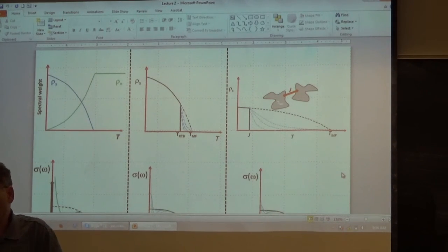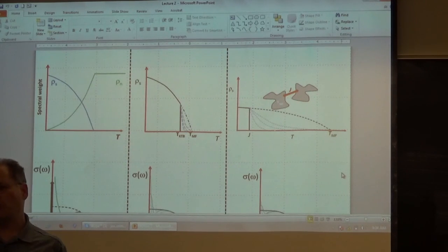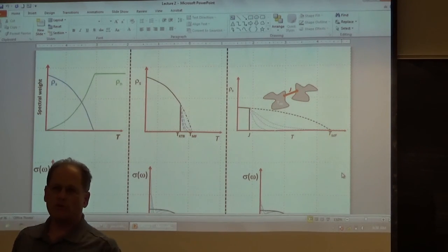I think that one of the interesting things about the cuprates is it enabled some very good experiments to be done by being able to work in a frequency regime where you could scan the frequency. Like conventional superconductors, these characteristic frequencies scale down to the microwaves. And for microwave spectroscopy, essentially, unless you do some very special things, you need a specific cavity setup for a specific frequency. So I've got a laboratory for 10 gigahertz, and if I'm really rich, I can have a laboratory for 10 and 30 gigahertz. So in the old days, everything had to be done at a fixed frequency, sweeping temperature and field. But cuprates enabled more experiments where you could sweep the frequency and learn a lot more.